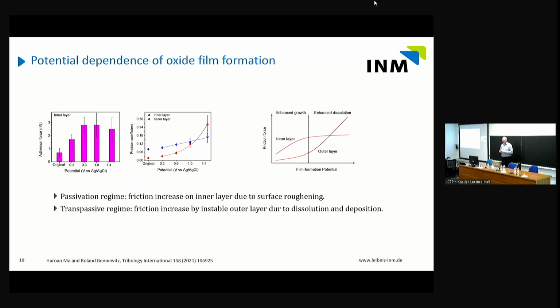Now, what about the potential dependence? We can, of course, measure the adhesion force, and we find that adhesion is going up if we oxidize with potential up to 0.6, and then it's flat. And the friction force for the inner layer increases with oxidation potential, and we believe that this inner layer is probably just roughened. So when we oxidize the inner layer, we get an oxide, and the oxide simply has a higher friction than the original metallic glass had. And the red dots in the middle frame are the friction according to the outer layer. So when we are still removing the outer layer, this goes through the roof when we oxidize at high potentials.